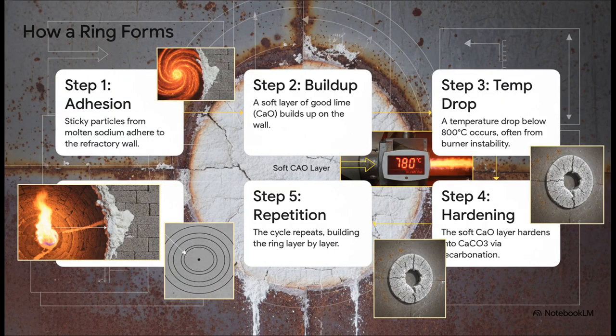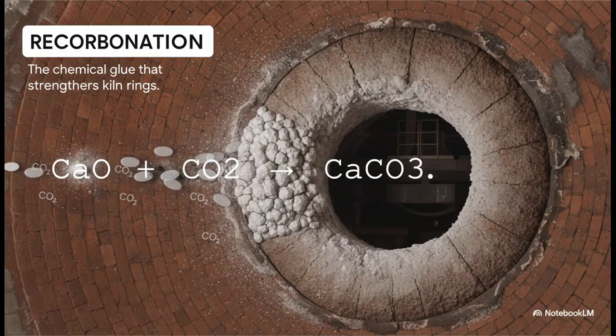So how does this actually happen? It's a nasty little cycle. First, those sticky particles from the molten sodium start sticking to the refractory wall. Then, a soft layer of good lime, our CaO, builds up on that sticky base. Now, here's the kicker. Step 3: you get a drop in temperature, maybe the burner hiccups or the feed changes. That temperature drop is the trigger for step 4. That soft, fluffy layer hardens up through a chemical reaction. And then the whole cycle just repeats, over and over, building this ring layer by painful layer, getting harder each and every time.